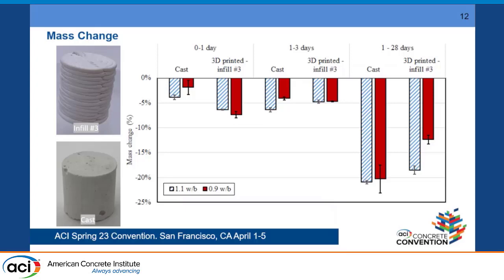So just by the fact that magnesium oxide is now 3D printed, we are observing a significant amount of carbon intake. The mechanical benefit is also that when magnesium oxide is hydrated and carbonated, it actually expands and increases in size, so all these pores are getting filled up with magnesium carbonate. So in fact, to be able to use the system, we'd rather increase its water evaporation, and that's where the mixture with the higher water to binder ratio, as you can see here with the 3D printed one, meant higher evaporation, higher carbon intake, and higher compressive strength.